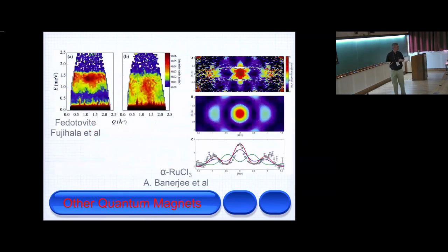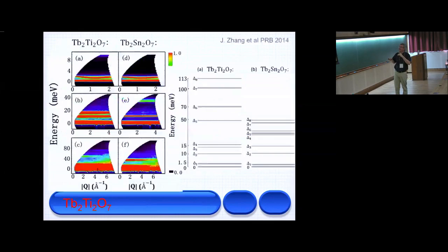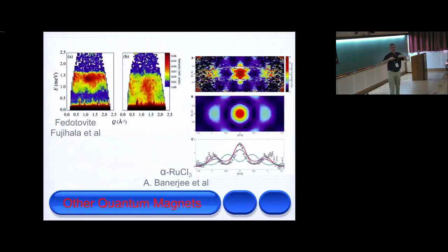At the moment, and this is my last slide, we don't, as was discussed in the first talk. And like terbium titanate, there's no Bragg peaks. We don't have any long-range order. In terbium titanate, we see some blobs. Sometimes you don't even see the blobs because the correlations are so weak. But what you see is the excitations from this liquid-like state.